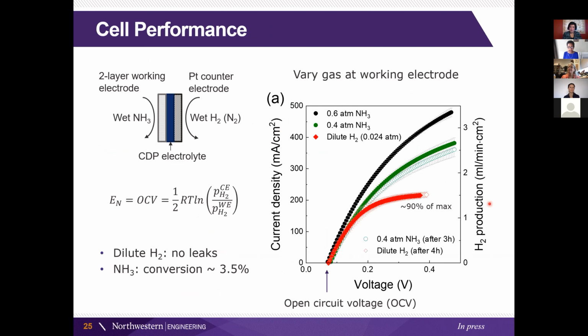Okay, great. And so let me show you what we then do. So now we have this two-layer electrode. Once again, we have an intermediate layer here of that electrocatalyst, which is platinum on carbon. That's a commercially obtained material. And that's mixed in with our electrolyte to provide the proton transport. And then we have our proton conducting electrolyte layer. And here we have that very easy to make platinum counter electrode, which has that relatively low platinum loading.